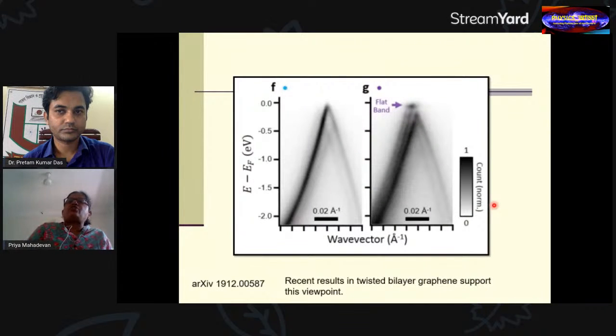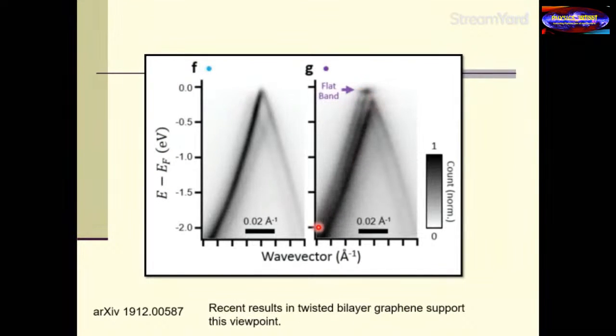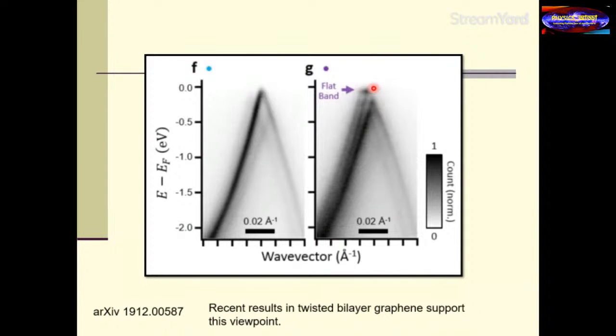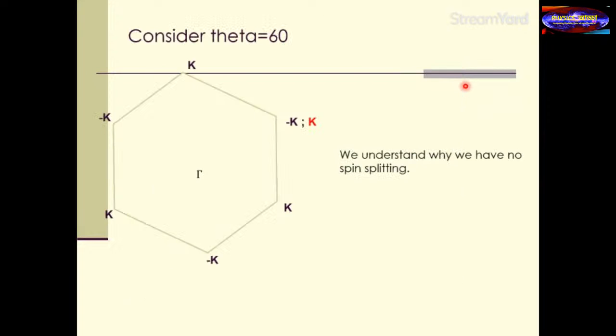Okay, and though this is not for the same system, there have been very recent experimental reports where angle-resolved photoemission experiments can determine experimentally the band dispersions for these materials, and they have taken twisted bilayer graphene. What they have seen is that the rest of the band structure is not like an isolated molecule where you should see only flat bands right through, but you have strongly dispersing bands right through, and then you have a flat band split off from the rest of the bands emerging.